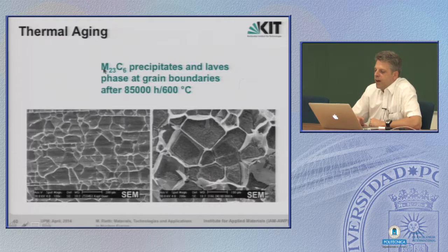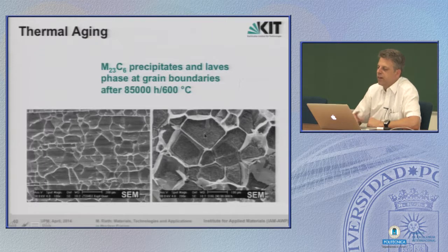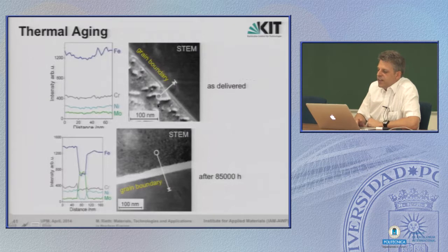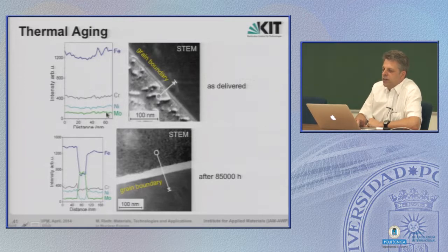Also, you see here an example where carbon-rich compounds, M stands for metal, metal carbides, if they can diffuse, they end up at the grain boundaries. In this image here we have dissolved the metal matrix with acid, and what remains is corrosion resistant carbides at the former grain boundaries, and this is also an aging effect. With a TEM, you can make a very good comparison. This is the 316 steel as delivered with a very thin grain boundary, and the change of the chemical composition over this grain boundary is almost not recognizable. It's almost constant. So a grain boundary has no negative effect on the 316 steel in the state as delivered.